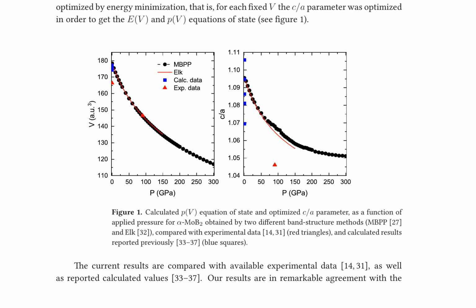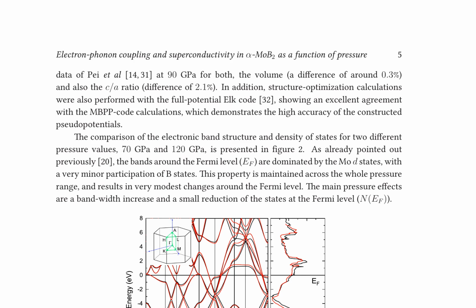The optimized c/a parameter is plotted as a function of applied pressure, showing remarkable agreement with experimental data and previous calculations. The frequency-dependent electron-phonon coupling, lambda of omega, is essential for understanding alpha MoB2's superconducting behavior. The Eliashberg function, alpha 2F of omega, is used to determine Tc by solving the Eliashberg gap equations numerically. Electron-phonon coupling and superconductivity in alpha MoB2 under pressure are the focus of this research.